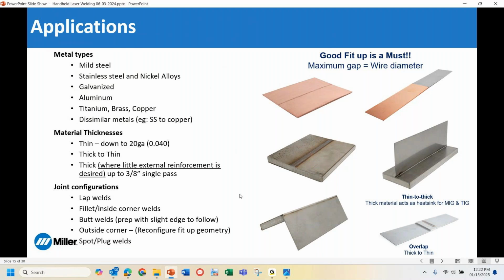You can even do dissimilar materials. If you imagine really high end kitchen accessories, a lot of times you might see copper to stainless steel. That can be done with this system. And then when we look at what a typical system, 2000 watts or less, is capable of doing, our particular system can do down to 20 gauge, maybe 22 gauge material, and then we can do up to 3/8 of an inch thick in a single pass.